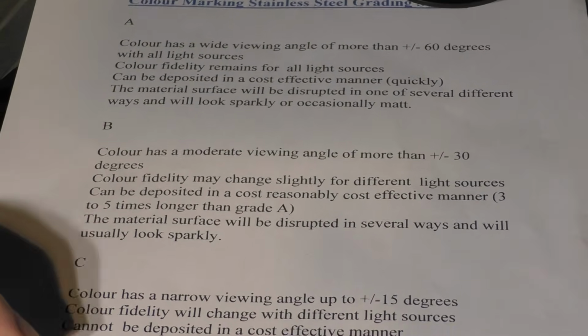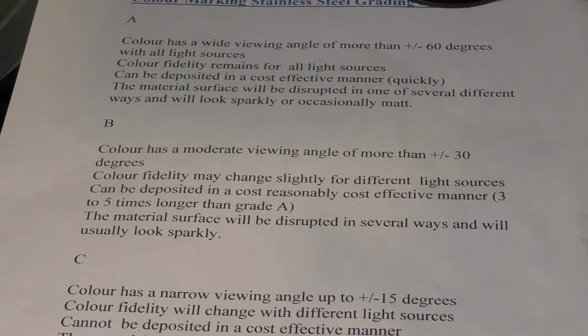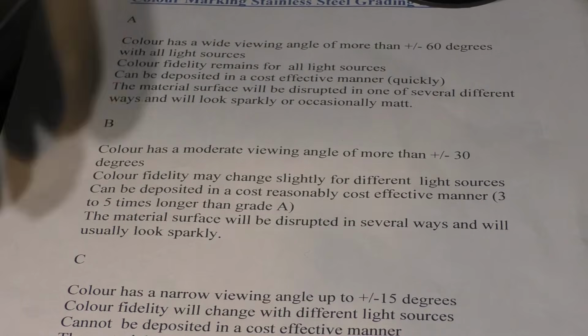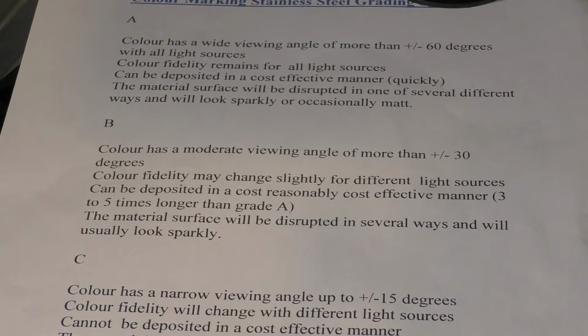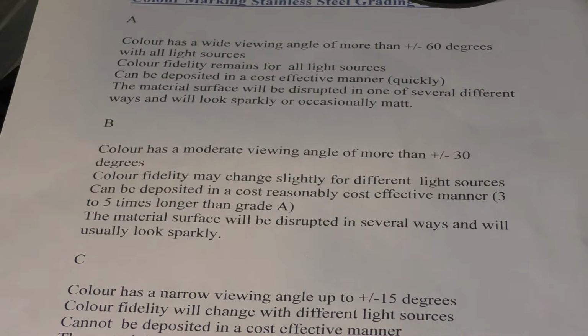C grade and D grade are very similar, except that C grade have got a little bit more viewing capability than a D grade, which is very limited at about plus or minus 10 degrees. And to be honest, most of the colours that you're going to encounter from other manufacturers who tout the colour chart as the best thing since sliced bread, it's not that good, because I wouldn't buy a machine based on something that I would class as D-grade colours.